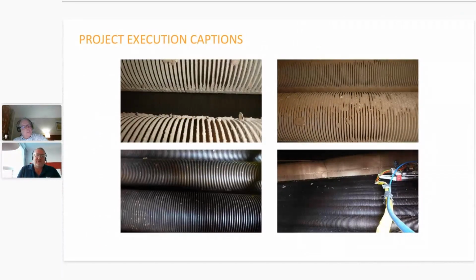So on first impressions, we found quite a bit of debris inside the unit. It was fouled quite heavily between the fins. And the build-up there was down from the top of the fin, as you can see in the pictures, all the way down to the root of the fin where it meets onto the tube. And you can also see some images there straight afterwards where we've cleaned these fins back to bare metal, and you get a situation where we know from visual experience that that will return the heat transfer, because we can see physically there is no deposit there anymore.